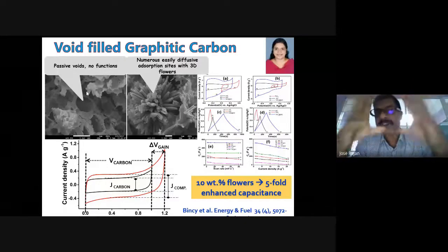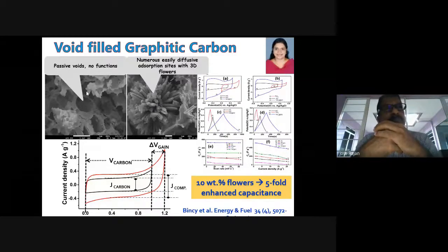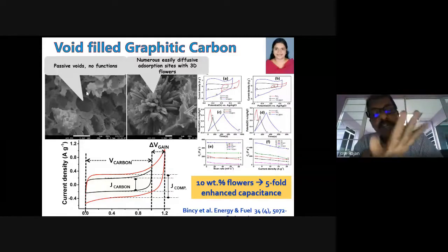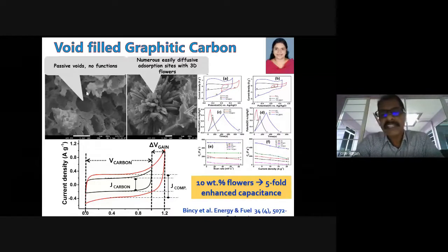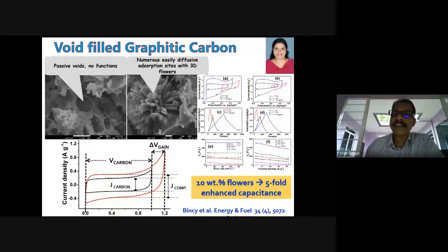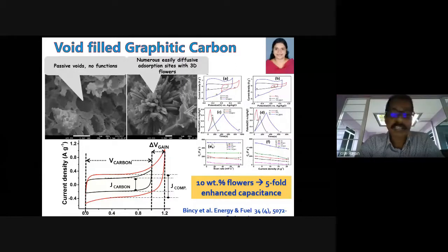Here we developed a carbon composite, where 90% is carbon and 10% is a nanoflower. The goodness with the nanoflower is it offers numerous charge diffusion sites, so that the charge storability in the resulting composite is high. To show that, look at the graph in the right panel, panel E. The top one, the blue line, is the capacitive charge storage by the composite, over 500 farads per gram, one of the highest ever reported using carbon. That is much higher than pure carbon, shown at the bottom as the black line.